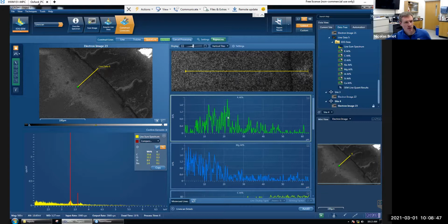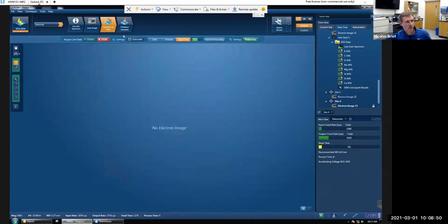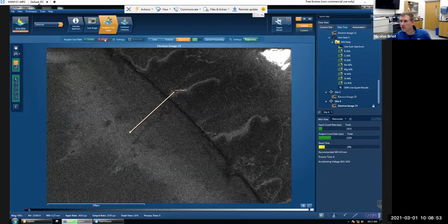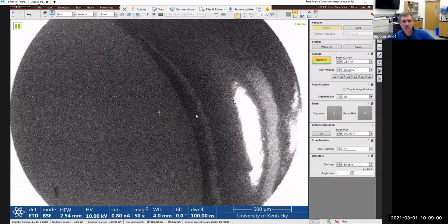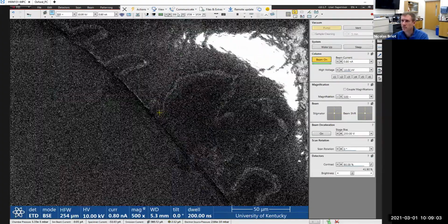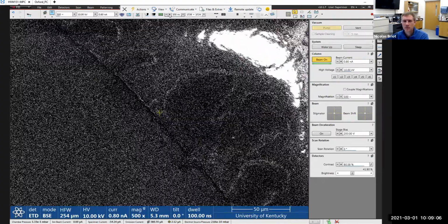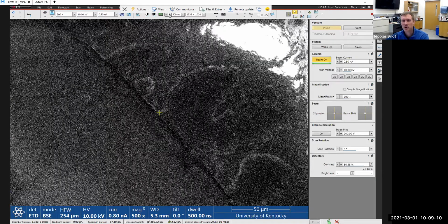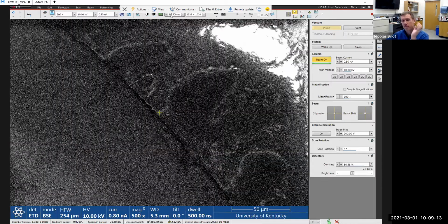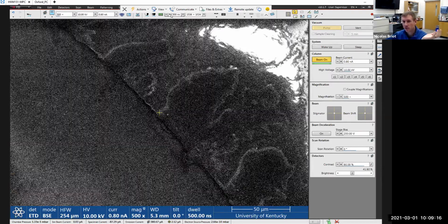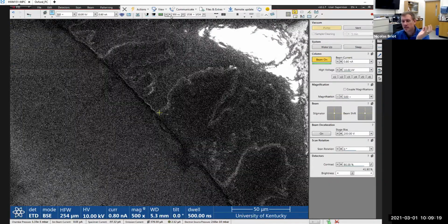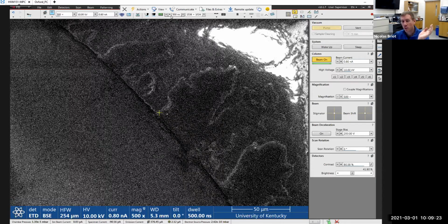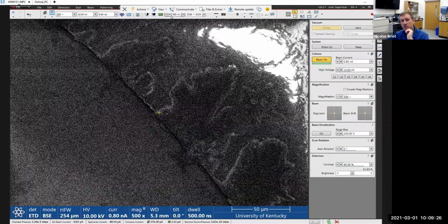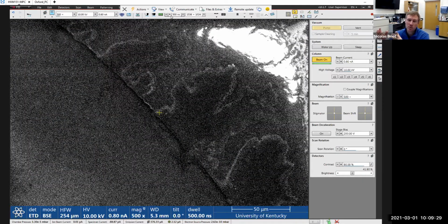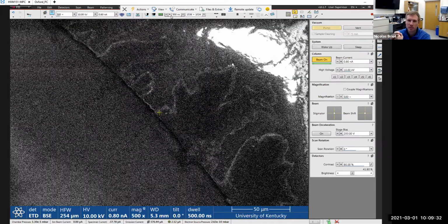I think what's happening is that it's not the sample that is moving. I need to check that. Yeah, okay. Let me show you what I see here. Depending on how fast or slow I scan, because of charging effects, the surface of the sample becomes negatively charged, so it's repelling the incident electrons. So they don't land where they are supposed to land. They land a little bit to the side of the regions that are really charged. This results in the image moving. The sample is not moving, the image is moving.